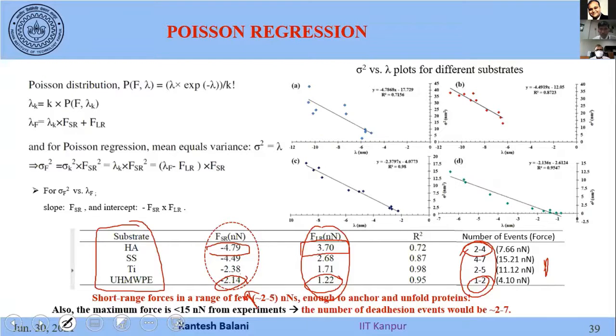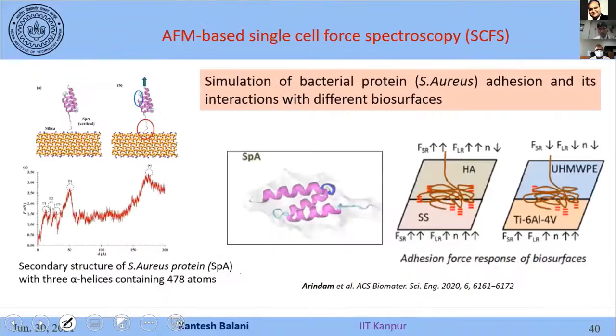So that's what I think it was able to highlight, the number of events and what is happening, especially for polymers. In summary, we are getting a very high level of long range and short range forces. For polymer, it was the least. We also did this test using horizontal and vertical orientations. For both of them, it was showing more or less similar response. There was not much difference.